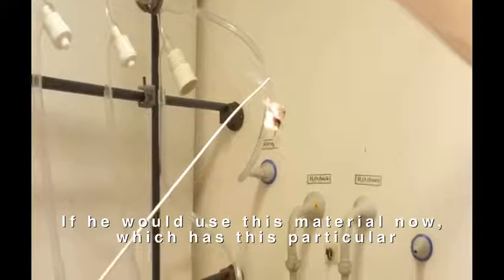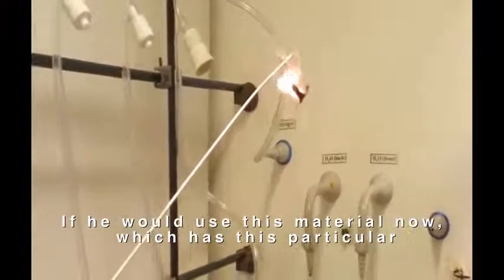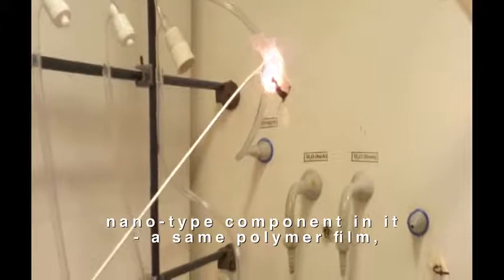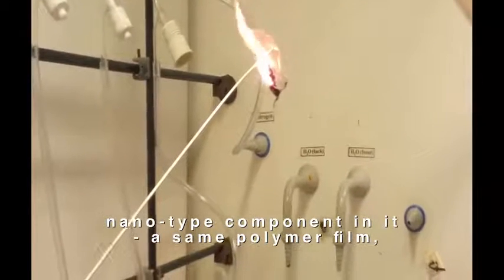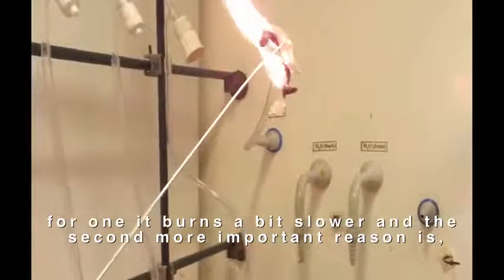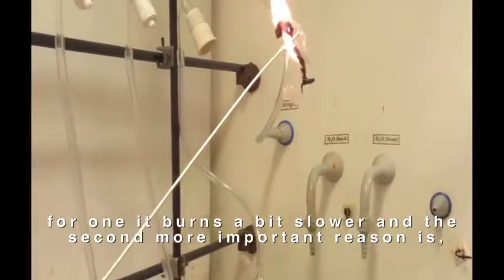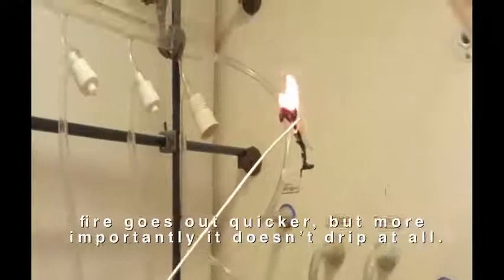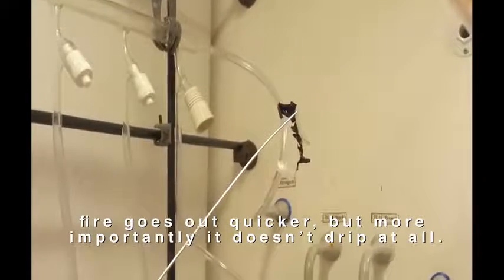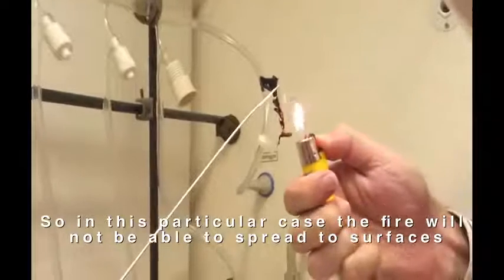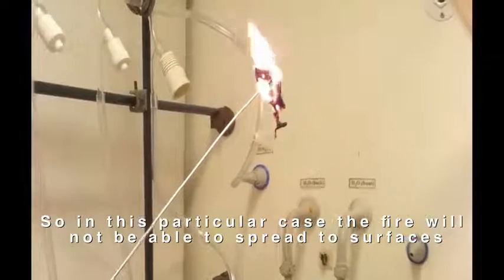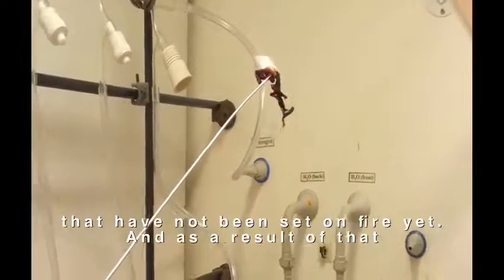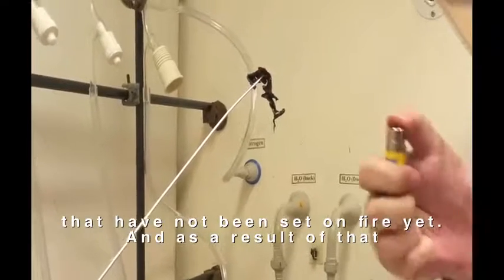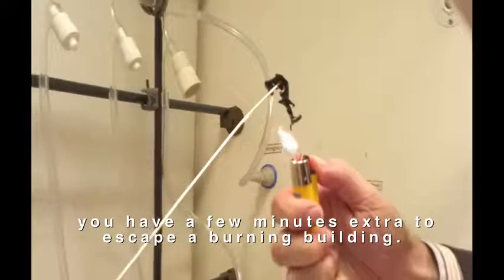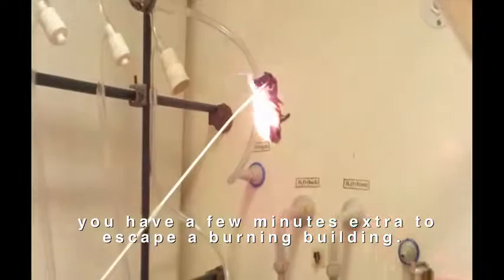If you use this material now, which has this particular nano component in it, the same polymer film burns a bit slower, and the second, more important reason is that the fire goes out quicker, but more importantly, it doesn't drip at all. So in this particular case, the fire will not be able to spread to surfaces that have not been set on fire yet. And as a result, you have a few minutes extra to escape a burning building.